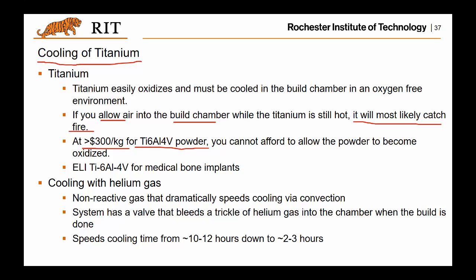So as we already know, you don't want to have oxygen inside the chamber. To make sure this is the case, you want to fill the chamber with helium gas during the cooling process of a part made of titanium. A good thing is that this helium gas speeds up the cooling process from 10 to 12 hours down to 2 to 3 hours, which is a significant reduction in cooling time.